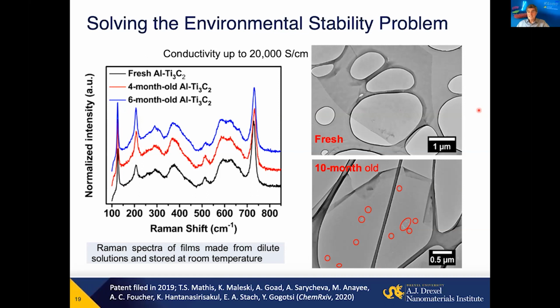What are the design parameters to look into in the case of scale up of the synthesis? In general, it's reproducibility and ensuring that whether we have 1 gram or 1 kilogram, we still have the same properties. We know it's scalable at least to kilogram. But what we would like to do is to decrease, for example, water consumption in washing the material. We want to be able to have less expensive precursors, MAX phases. For example, titanium carbonitride, Ti2C, Ti3C2 MXenes, made of very abundant elements, titanium and carbon. So if we find a way to have a low-cost, scale-up method for the synthesis, we will have a really great impact on the technology with these materials.